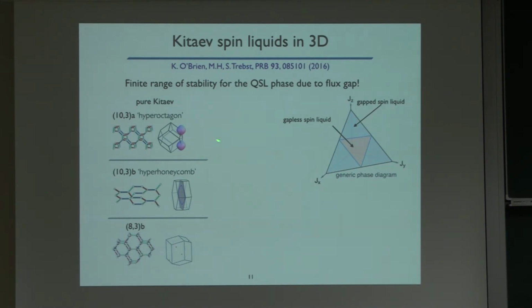So let's first look at a generic phase diagram. The phase diagram is actually more or less always the same no matter what lattice you put it on. Details may change, but it's always the case that if one of the coupling constants is much larger than the other two, then you're in a gapped spin liquid regime. If they're all approximately the same, you're in a gapless regime. The phase boundaries really depend on the lattice and what you're looking at. So we're going to focus on the gapless regime here, and we're going to ask ourselves what kind of dispersion relations can the Majorana fermions form, and that really tells us what kind of quantum spin liquids can we have. And what you see here is that you have a lot of freedom, so these Majorana fermions can form anything from a surface over nodal lines to Weyl points. And what you get really depends on the lattice.